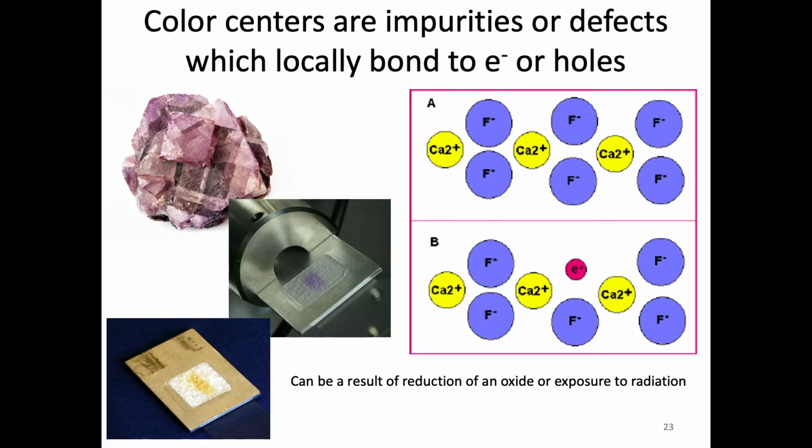In 407, you didn't get to see this in person this year, but when we're conducting X-ray diffraction, a source of radiation, sometimes certain crystals like this, or the glass slide that we actually use, can become colored from radiation. The spot that's purple here or yellow here is where there's a high concentration of radiation in the form of X-rays, and that causes these defects, these color centers, to emerge. That's another way we can get colors from these color centers.